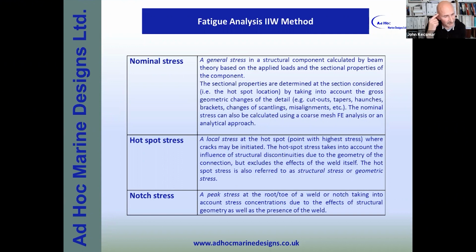However, today, there are means and methods to try to address this. There is a fatigue analysis method by the International Institute of Welding, and they've spent some 10, 20, almost 30 years now performing a lot of R&D. And there's essentially 3 routes that the naval architect can take in order to assist in this particular process. They are termed the nominal stress approach, the hotspot stress approach and the notch stress approach.